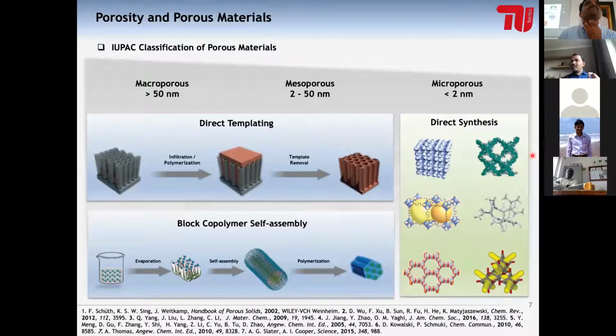The first example could be zeolite, where metal centers are coordinated through oxygen with each other, creating the microporous material. In metal organic frameworks, for example, metals are coordinated to the next metal through the organic linker. And in covalent organic frameworks and porous polymers also, organic linkers are coordinated with each other through covalent bonding. That is why you can maintain the porosity depending on what kind of pore and what kind of materials you would like to have. And this can be tuned just by changing the metals or organic linkers.